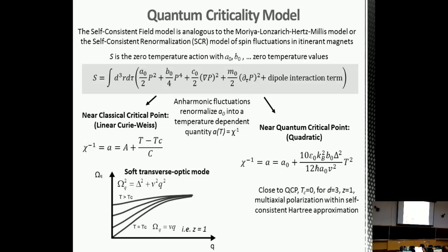And in the limit close to the quantum critical point, you can actually express it in a closed-form analytical solution here, where these parameters, delta and v, are the optical phonon gap and the speed of the phonons as the gap gets lower. And A naught and B naught here are the parameters from the equation of state. So these are determined from independent experiments at zero temperature and are not fitting parameters in this theory.